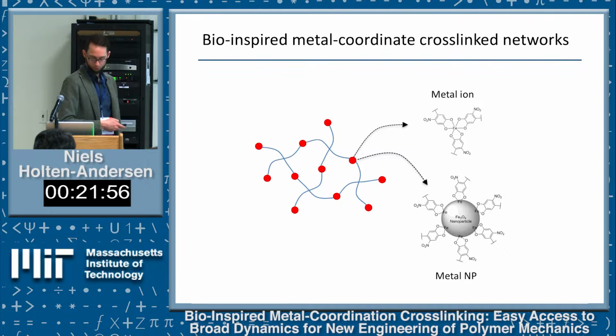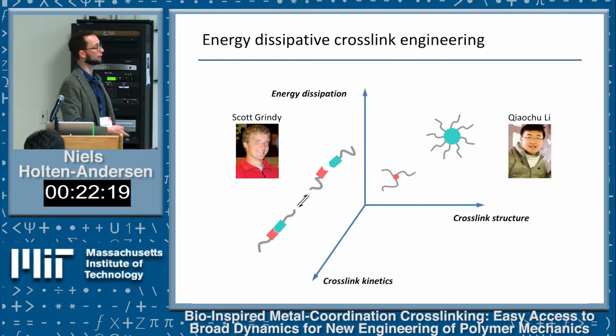Okay, so for the last 15 minutes, I'll tell you a little about what we've been doing with the nanoparticle cross-linking gels. This is a very different type of cross-link—relatively much bigger than a metal ion. So you're going to get many more ligands binding each particle than you would binding a metal ion, and that's going to dictate the mechanics into a much more solid-like regime.